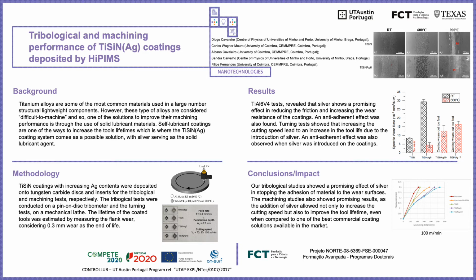Adding to this, another interesting result we found was the added anti-adherent effect of silver at high temperatures, which could see potential use in reducing the formation of built-up edges during the machining process. Lastly, for our turning tests, we can see that for higher speeds, the addition of silver shows a beneficial effect in increasing the tool lives, even showing higher tool lives than that of the industrially used aluminum titanium nitride we tested.